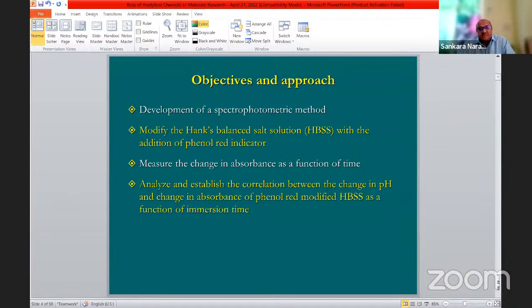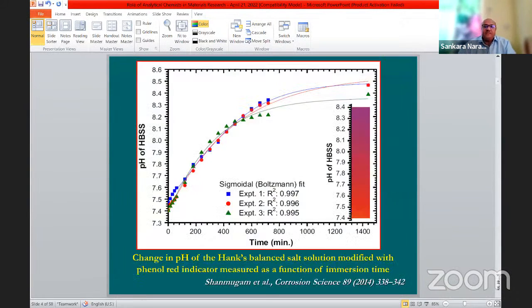In the process, our main aim is to analyze the data and establish whether there is a correlation between the change in pH and the change in absorbance of the phenol red modified solution as a function of time. If there is a good correlation, then we can monitor the rate of corrosion, or the corrosion behavior of magnesium, by spectrophotometry. That is our idea in this method. So we initially measured the pH of the simulated body fluid modified with phenol red as a function of time. Initially, this is the color of the solution, and as a function of time we monitored the change in pH.